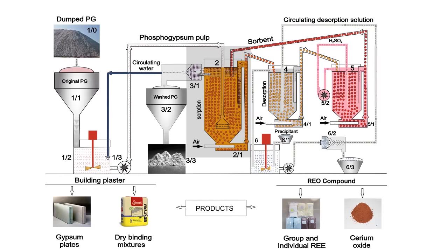At the second step, sorption leaching of the REE from phosphogypsum is carried out in pulse columns, position 2. For this, a phosphogypsum pulp is fed through a distribution comb to the bottom of the column, and strong acid cation resin, meaning sorbent in H+ form, from the top of the column. Sorption leaching of the REE from phosphogypsum is carried out by a counter-movement of the pulp and sorbent, respectively pulp bottom-up and sorbent top-down of the column.